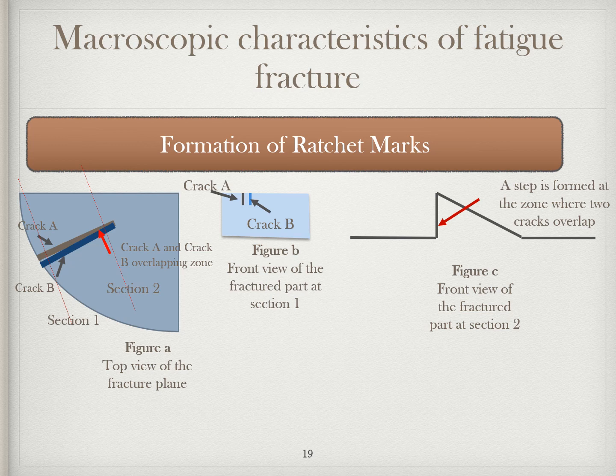The ratchet marks are not the origins themselves. Each ratchet mark separates two adjacent fatigue fractures. As the crack becomes deeper, the cracks from each origin tend to grow together and become essentially one fatigue fracture that has numerous origins. The number of ratchet marks equals, or is one less than, the number of origins. Thus, recognition of the number of ratchet marks is important in determining the number of origins.